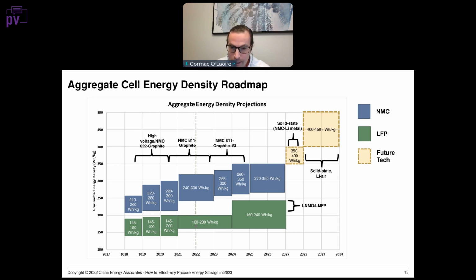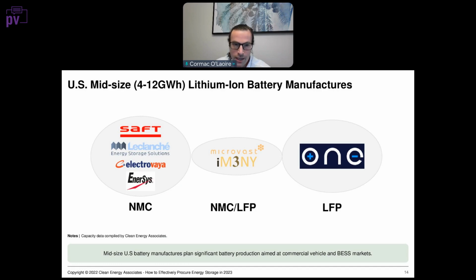We have lithium manganese iron phosphate as one potential candidate, and we have lithium nickel manganese oxides. The spinel type structures are really attracting attention in the industry in terms of increasing gravimetric energy density. So we see LFP remaining globally as the cell of choice for BESS energy storage systems. But as I mentioned earlier, the US battery announcements and industry is more or less focused on electric vehicles, and they're working with NMC type chemistry.